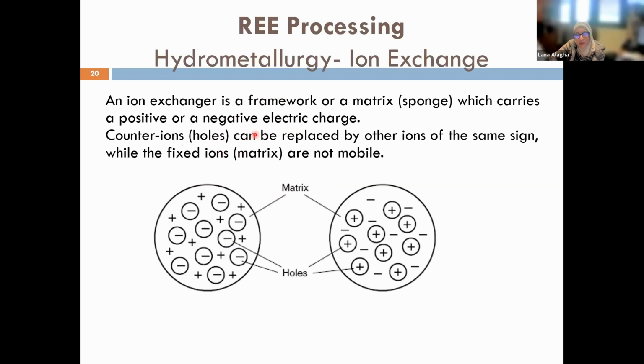We call it ion exchange resin. It is like a sponge that has two parts. One of them is fixed, and one of them is mobile. The mobile part has ions that can be exchanged with other ions from solution. So when you exchange these ions from solution to the resin, it means that you are removing the ion you want to separate from solution to the body of this resin. And then you separate your metal ions of interest by absorbing them on the resin. After that, you can strip off these ions that were previously absorbed and get them back in solution. But in this case, the solution will be purified.